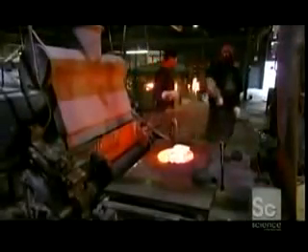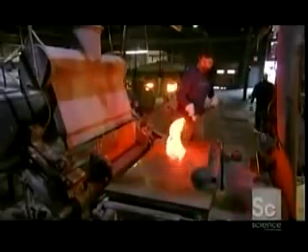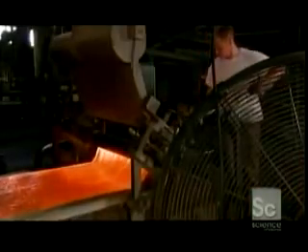The mixing table is where the magic happens. The table worker picks up one gather of burning molten glass, then another, then skillfully blends them together using a steel fork. He then flips the molten glass into a rolling machine, evening it out as it squeezes through the rollers. Out comes a sheet about 6 feet long and 1/8 of an inch thick.